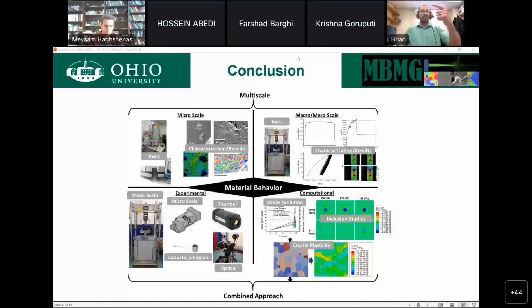The other benefit is we're sending energy through. So we know the material we're building. We know what its wave speed should be if it's built well. So we know how long it should take at every layer to receive energy from when it gets sent, which means if we see a change in that, we know there's a buildup of porosities, a buildup of defects. Depending on the frequency of the wave that you're sending, you can see small defects or large defects. The 28 kilohertz we're using is only for large defects or large amounts of energy.